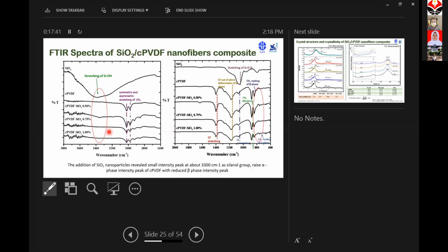So we observe the silica cPVDF nanofiber composite by using FTIR spectra. By using infrared spectra, we can also observe the crystal phase of the polymer, for example PVDF, because PVDF or PVDF copolymer is polymorphic. So we can see in the FTIR spectra that the polymer has alpha and beta phase crystal structure. You can see here, this is alpha phase, and here is beta phase.